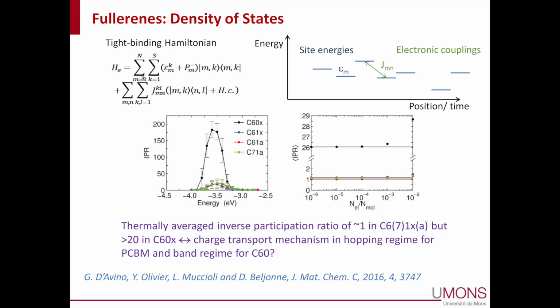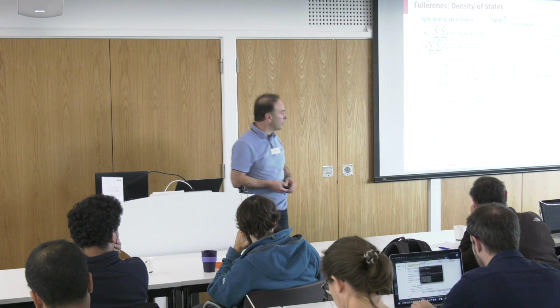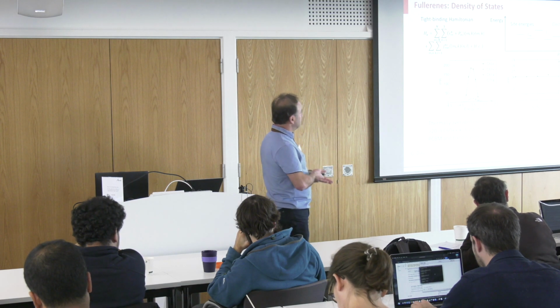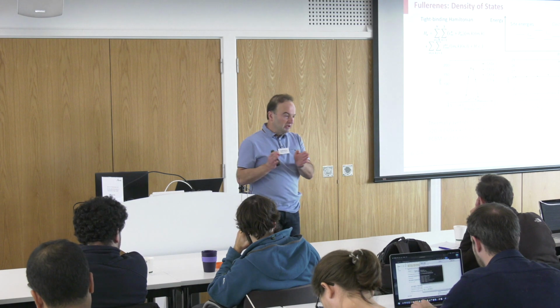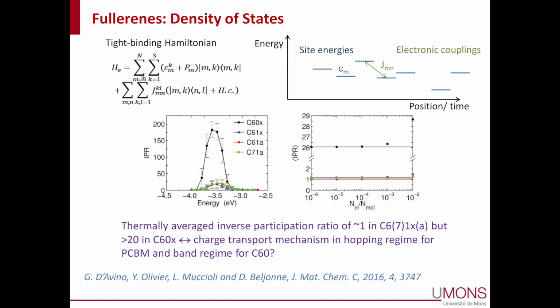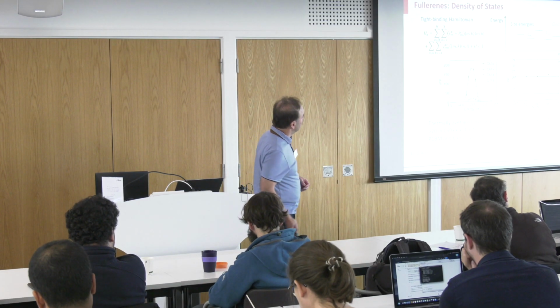So you end up with an energy landscape that looks like this, the density of states, where the tail of the distributions, especially for the soluble version, are essentially confined over a single molecule. But that doesn't prevent the center of the distribution from having delocalization that can be up to 20, 40, or even more molecules. So then the question of localization or delocalization of those materials will depend very much on the energy at which you're probing. In principle, in equilibrium conditions for a C60 derivative, for charge transport, you would probe the tail of the distribution, so essentially a hopping model would seem appropriate. But if you can reach the states in the middle, then you might take advantage of the extended delocalization of the electrons.